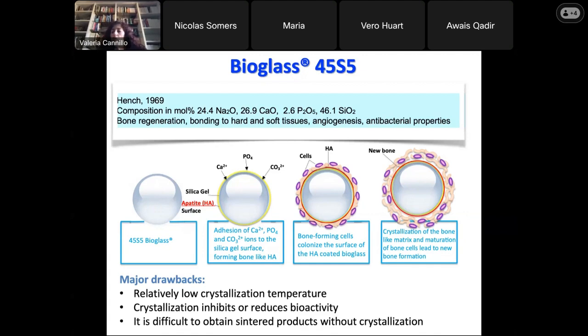Moreover, it should be stressed that the regenerative potential of bioactive glasses is strongly influenced by their ionic release, which may be too slow in partially crystallized samples. Unfortunately, the optimal sintering temperature for 45S5 is between 1000 and 1100 degrees to realize scaffolds. So the crystallization temperature is reached, and so there is a wide devitrification of the system.